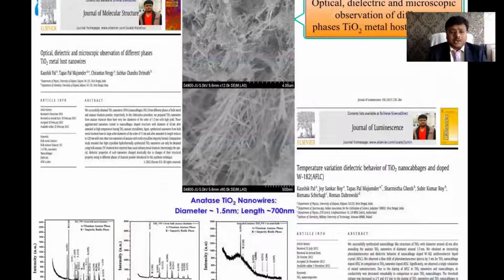This is TiO2 nanowires. It's a basic material. We started with bulk anatase TiO2, which can have different phases: rutile, brookite, and anatase. So basically we started with anatase. You can see here in the XRD there is a lot of rutile peak, an impurity peak. So we washed several times with HCl, the same procedure which I previously discussed.